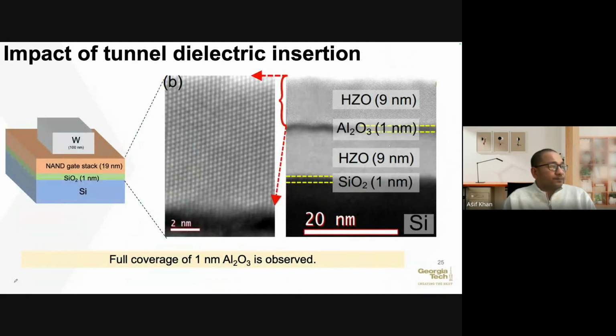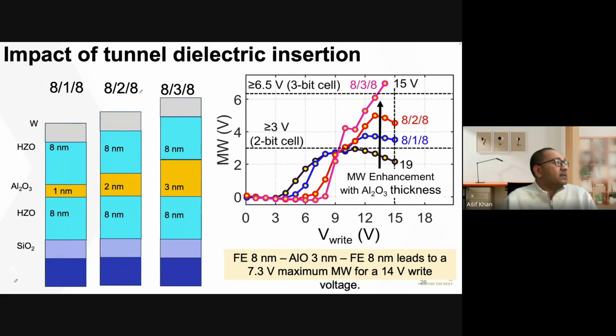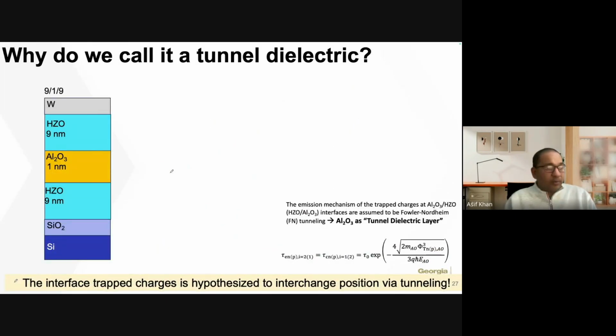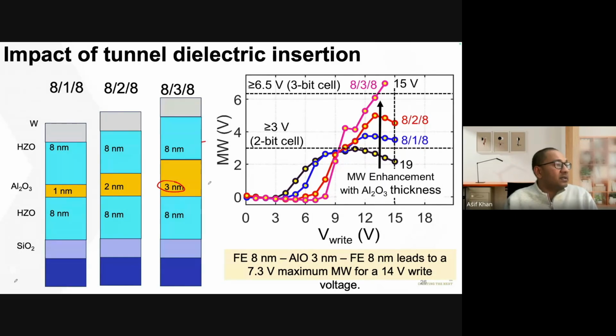Going forward, we tried a bunch of different stacks, and in this process, what Dr. Das found was that as you keep on increasing the alumina thickness while keeping the other layers the same, the maximum memory window keeps on going up. And finally, after trial and error of 6 months, we were able to get a memory window that is larger than 6.5 volts for a write voltage smaller than 15 volts, which was our target. And that was the first time that anyone could show that we can beat these limits within the thickness range of 19 nanometers, the voltage range of 15 volts, and achieve more than 6.5 volts of memory window.